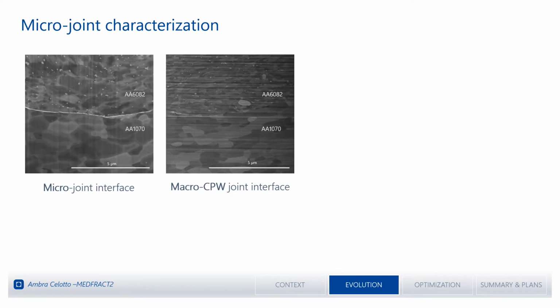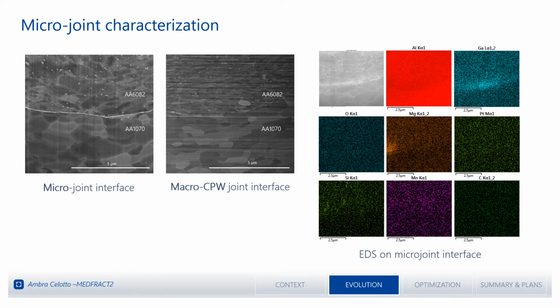But if we try to compare this microjoint interface with our reference macro scale pressure welded joint, we notice this white line in the interface that doesn't match the macro scale sample. And by doing EDS analysis, this revealed to be gallium implanted in the interface. This is actually a quite well-known problem when one talks about aluminium inside a gallium FIB. And this is because aluminium is very sensitive to gallium. Gallium is able to diffuse quite well along the grain boundaries of aluminium, and this often results in a weakening effect on the aluminium. The gallium is able to weaken the strength up to a factor of 10.